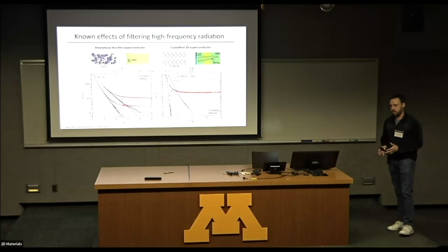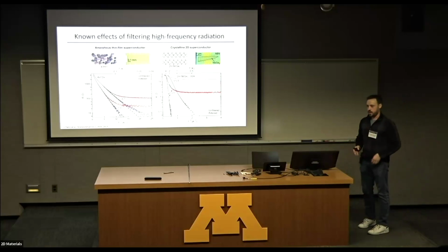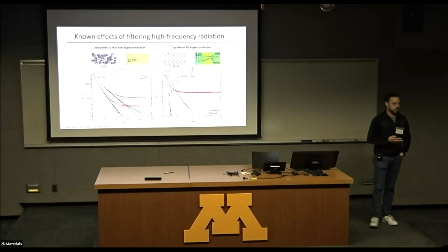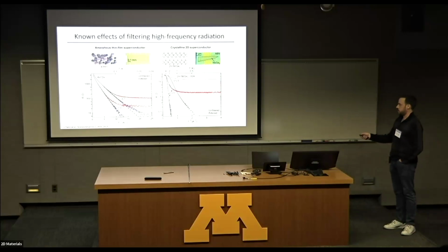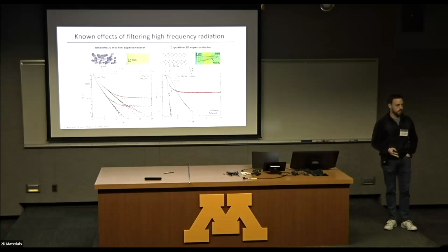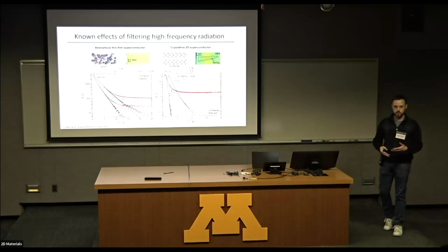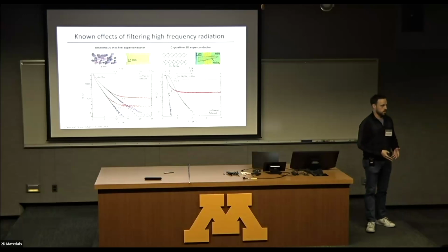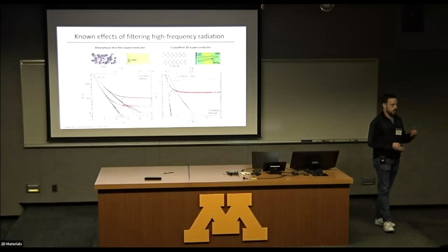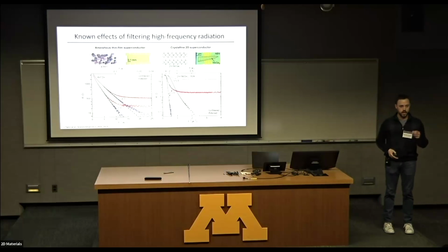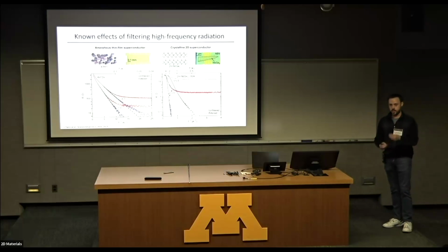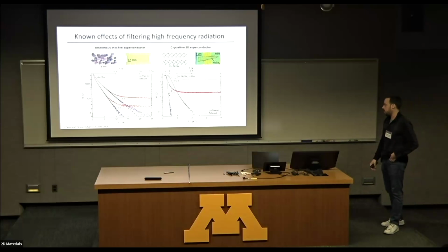Of course, one must also be very careful because there are known reasons why a true superconductor can mimic this so-called anomalous metal. So here's work from Danny Shahar's group that shows that whether you look at amorphous thin film superconductors or crystalline 2D superconductors, just as examples, if you don't properly have good low temperature filtering in your DC lines doing transport, then microwave photons can come in and generate Bogoliubov excitations that will heat the system as they relax.